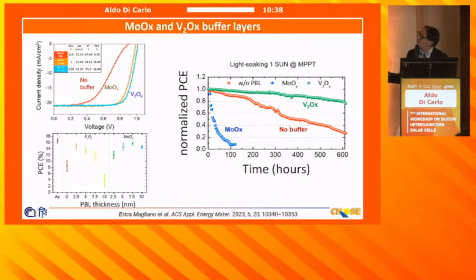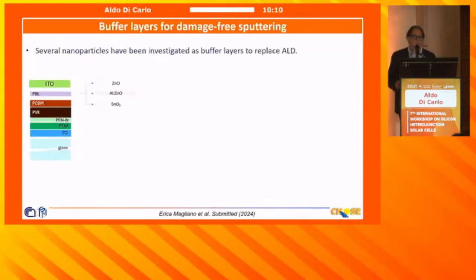This is the light soaking at 50 degrees. Without a buffer, you have this kind of behavior, and with molybdenum oxide you have a very strong reduction of efficiency. There is a reaction, which is quite well known. But with vanadium oxide you have a much better result, so vanadium oxide is one of the choices for us to use as a buffer layer. Another way to do it is to use a nanoparticle layer instead of ALD.